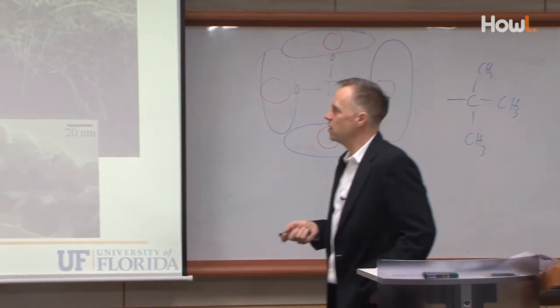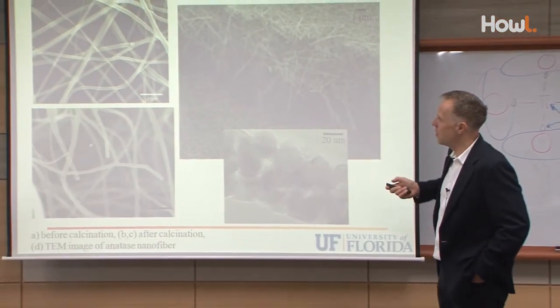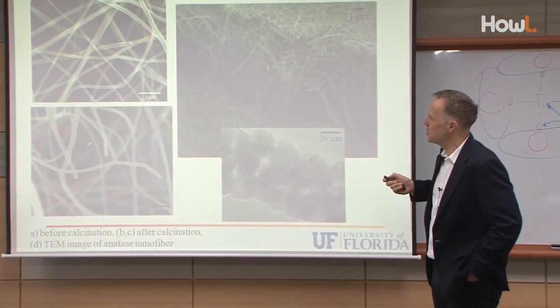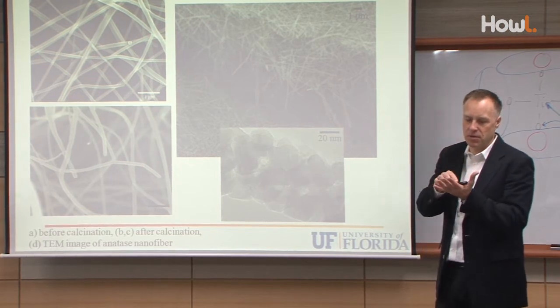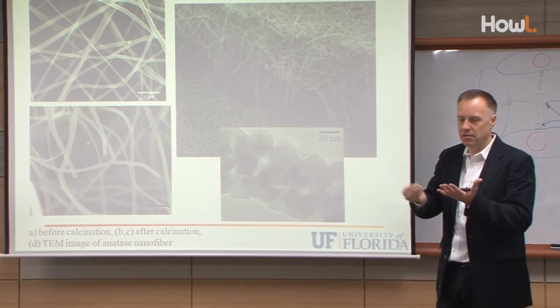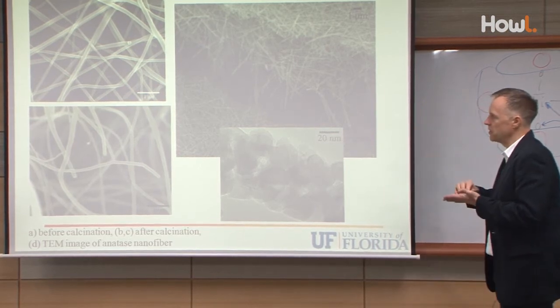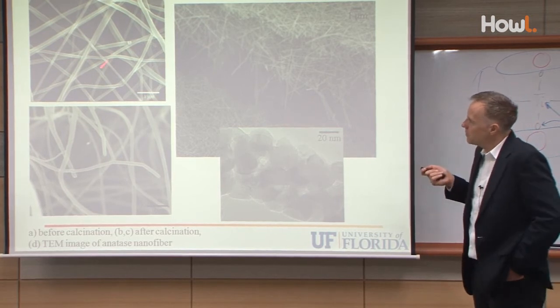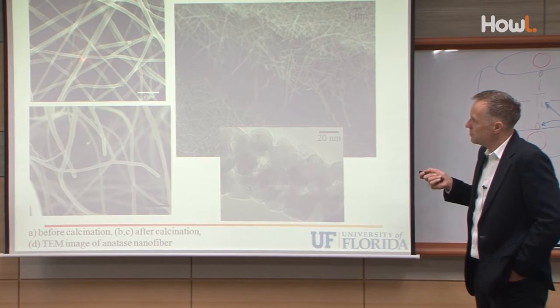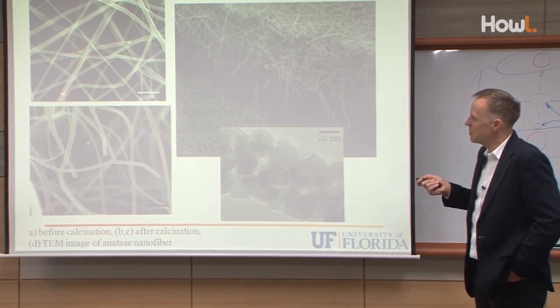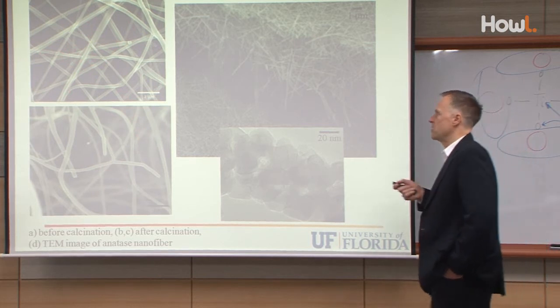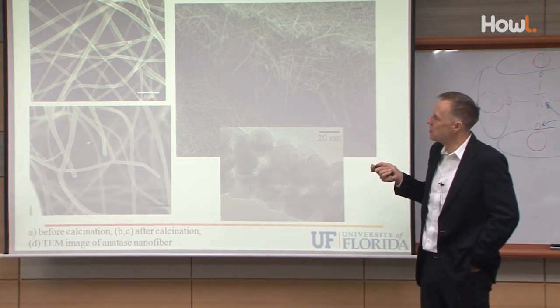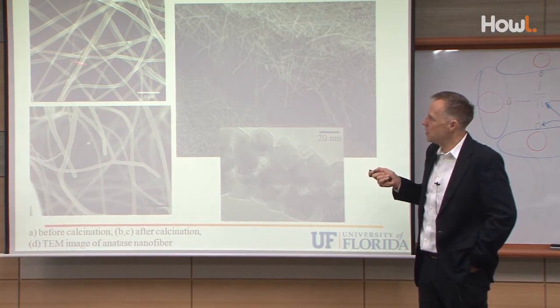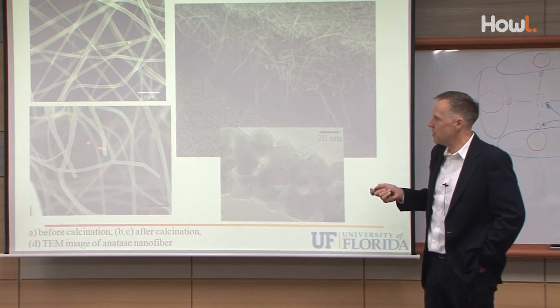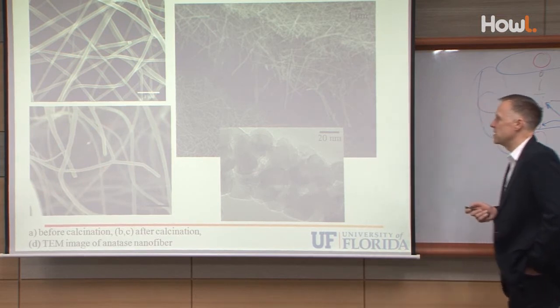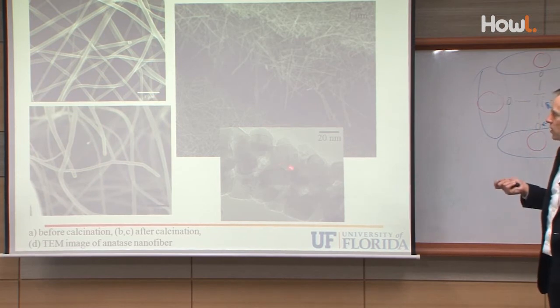So if you electrospin them, yeah, you get the fibers. This is as received, like the earlier picture. Depending on the deposition conditions, you might have fusing of these fibers because you have wet polymer systems coming down, depositing on each other. And when they're too wet, basically they can fuse and connect. But if you heat the system or use ethanol, it evaporates usually quickly enough. If the distance is long enough between the fiber and the target, then you are successfully making single fibers. And when you heat treat them, of course, sometimes they break. Especially these materials break rather easily, the titania, because they're not single crystal fibers. They're polycrystalline.